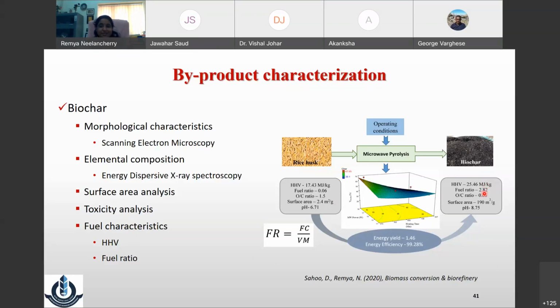So lesser oxygen, of course, is giving us a hint that it has high heating value. And you can see the tremendous improvement in the surface area, and we could use it for the adsorption of several compounds, like even nitrate and phosphate removal from wastewater as well. And the improved pH was also observed. So it is giving a hint that if I need to use it as a soil amendment in an acidic soil, it may give you some improvement or soil conditioning.